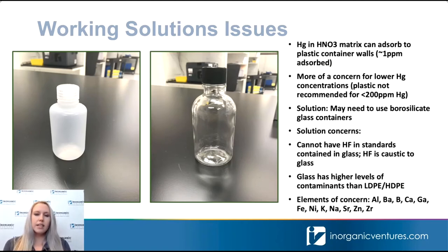One option to prevent mercury adsorption is to keep your solutions in glass instead of plastic. However, this adds more concerns because if you have hydrofluoric acid in your solutions, it is caustic to glass, so you can't keep those solutions in a glass container. Another concern for using borosilicate glass vessels is that glass is going to have a much higher level of contaminants. So if you're analyzing for any of these elements that I've listed here in the lower right of the screen, you definitely don't want to be using a glass container, as this will add additional contaminants of those elements.